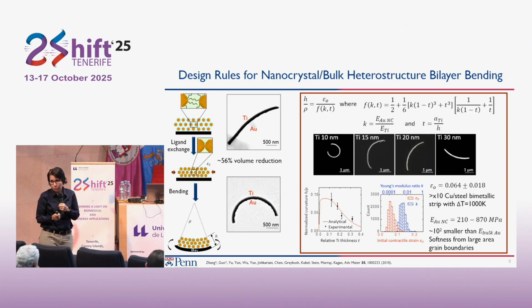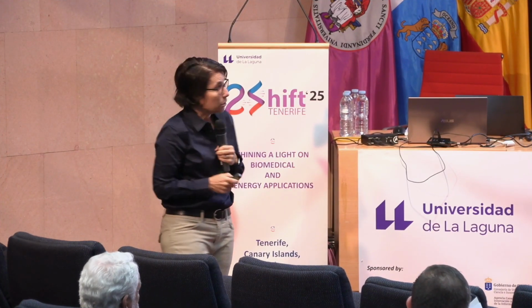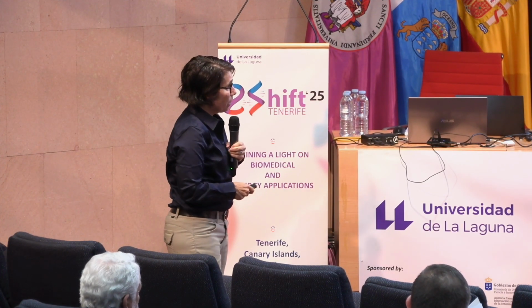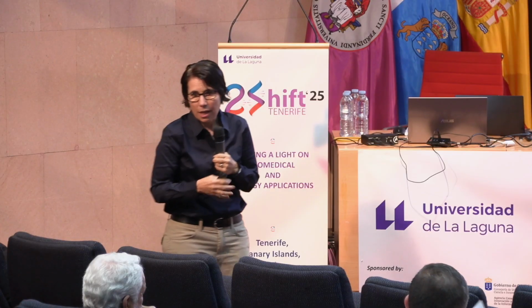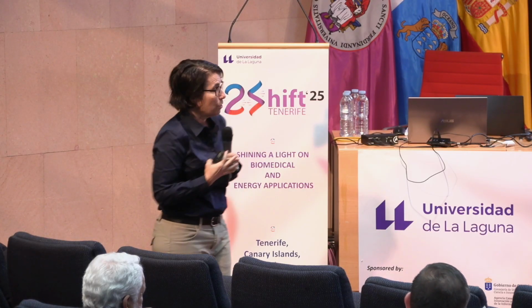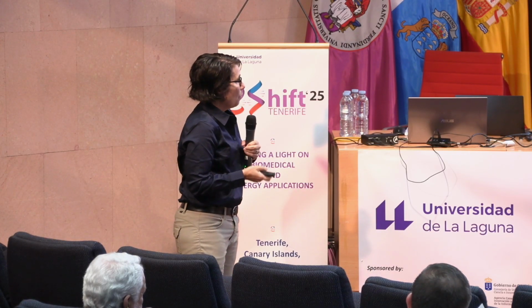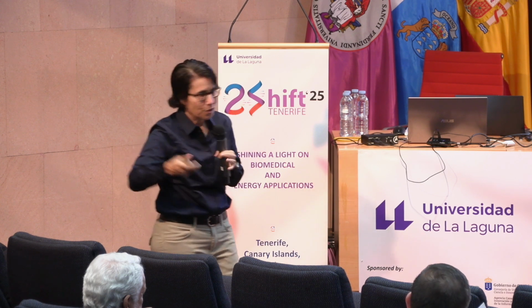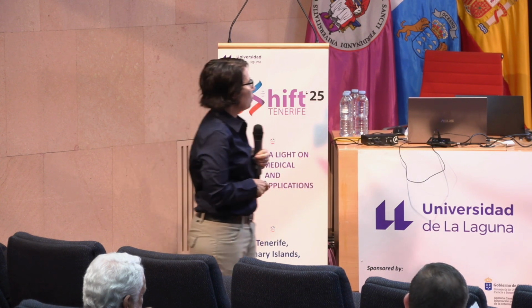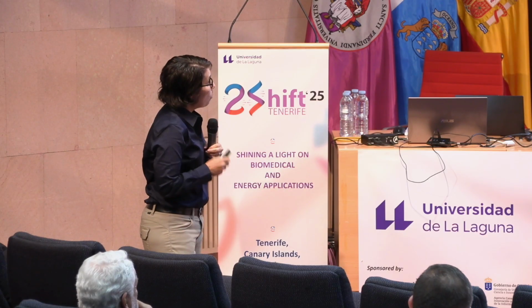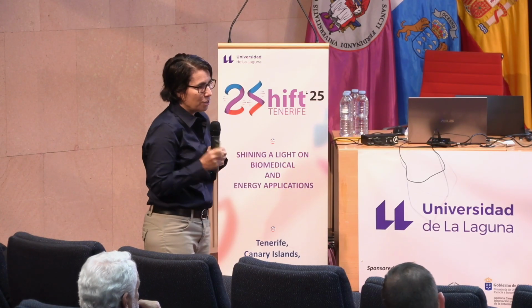The other thing we could learn about is the Young's modulus of the nanocrystal layer. And you can see here these materials are actually quite soft, right? Originally, and so consistent with this idea that you fold them. And actually, if you anneal them, we could go further, and you'll see that we could get even higher strains and such.